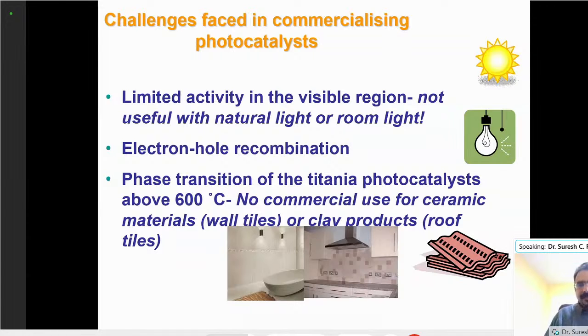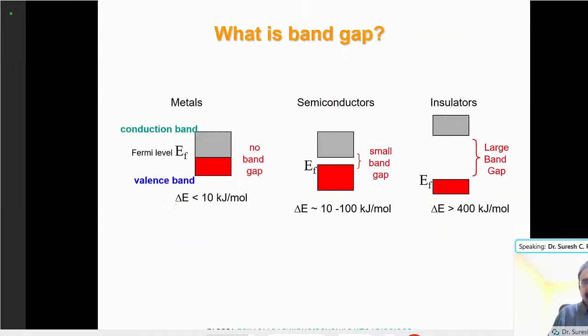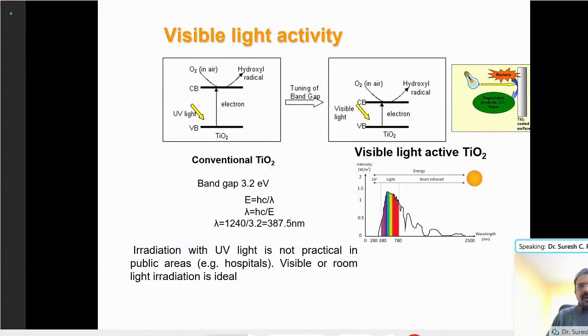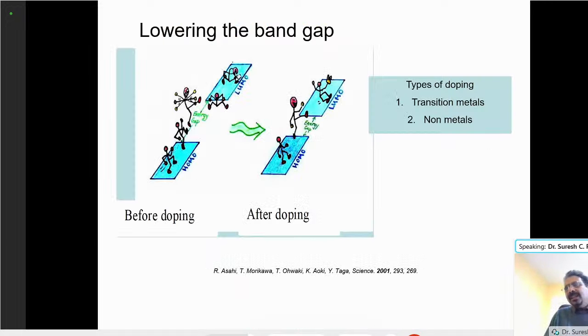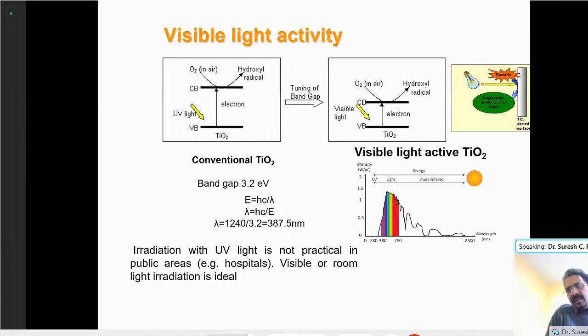The problem here is, so I'm going to skip a few slides. The problem here is the anatase form of titanium dioxide, which is the normal state, converts to rutile, which is a non-photocatalytic phase at high temperature. So you cannot use the normal photocatalytic material, which changes to a non-photocatalytic phase at 600 degrees. So that is one problem.